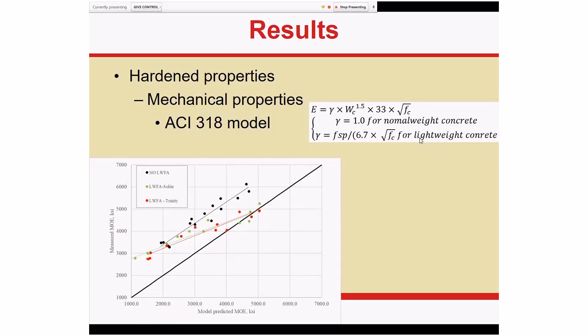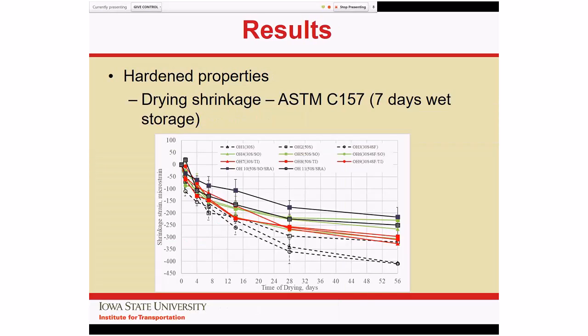Now, from a structural design point of view, we just compared the ACI 318 model for the three different aggregate systems, and the conventional aggregate system ran parallel to the model. The two lightweight systems did not. So again, it may have to come back to the bridge designers, when you're looking at some of the other aspects of thickness design and cracking risk, is that the 318 model doesn't work for these materials. We need to recalibrate how we apply that term into any modeling that we do.